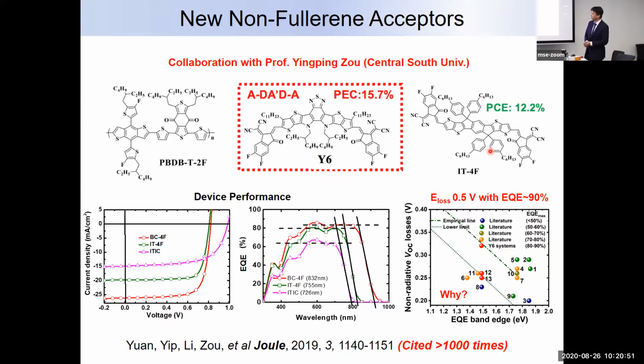Anyway, although we have put a lot of effort into improving the performance, the underlying principle or fundamentals about why this new type of acceptor material has improved performance is still unknown. But if you look at this Y6 molecule, compared to the previous champion non-fullerene acceptor, Y6 is smaller in bandgap. That means it can absorb more light, okay? But if you look at their VOC, it is the same as with IT4F. Therefore, you get very good EQE, very high current density, and also maintain a reasonable VOC. So now you can immediately get power conversion efficiency close to 16%.